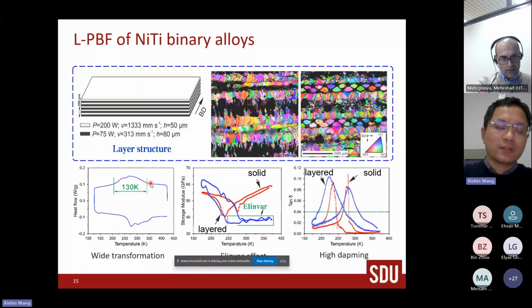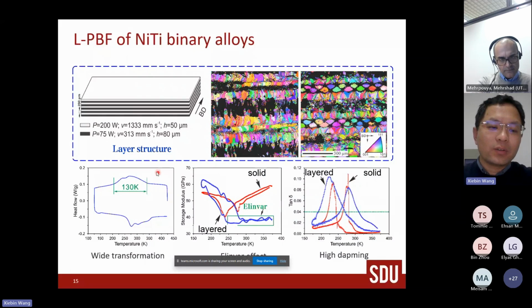For example, for the conventional nickel titanium alloys, the temperature range between martensite transformation start temperature and finish temperature is around 20 to 40 degrees. But this material shows a very wide transformation interval of 130 degrees. And with such a wide transformation interval, it gives you a lot of interesting phenomena like the Elinvar effect.